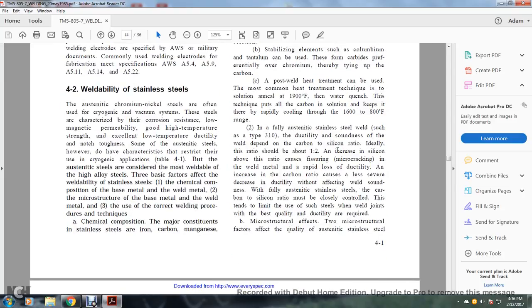2. In fully austenitic stainless steel welds, such as type 310, the ductility and soundness of the weld depend on the carbon to silicon ratio. Ideally, the ratio should be about 1 to 2. An increase of silicon above this ratio causes fissuring or micro-cracking in the weld metal, with a rapid loss of ductility. An increase in the carbon ratio causes a less severe decrease in ductility without affecting weld soundness. With fully austenitic stainless steel, the carbon to silicon ratio must be closely controlled. This tends to limit the use of such steels where welded joints of the best quality and ductility are required.